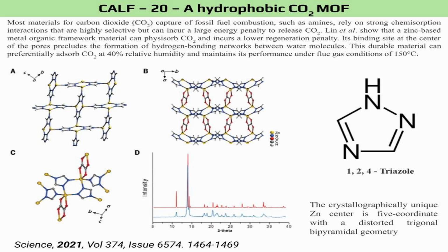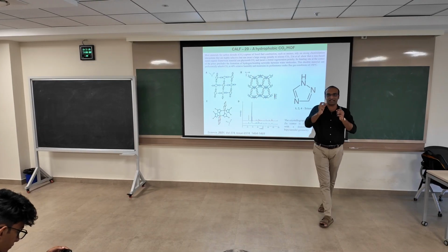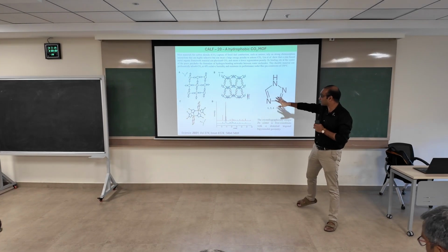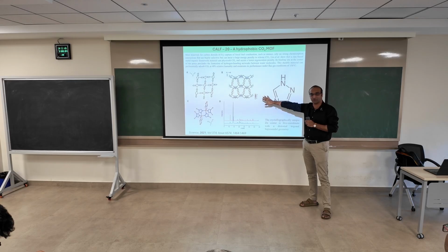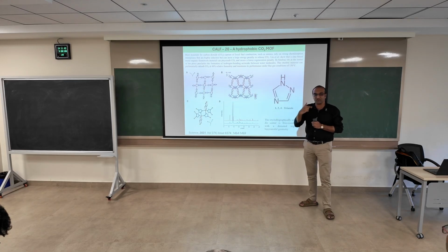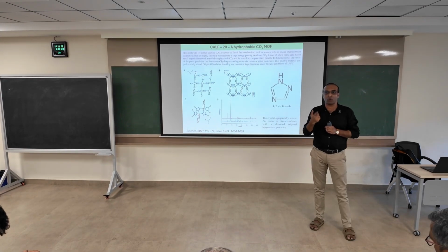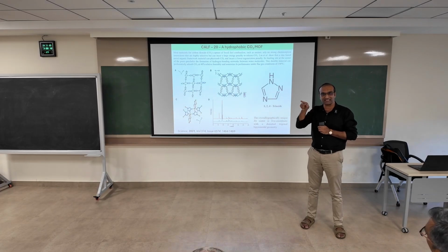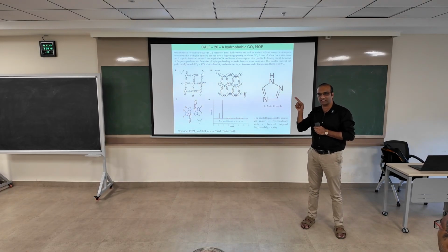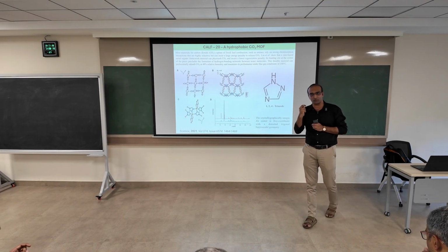On top, it's one layer where you have this zinc and this coordinated weakly, okay? And then you have these layers in between, they're connected through these oxalic acid linkages, okay? But the unique thing about this MOF, and the reason why I'm showing it, is it has a preferential adsorption for CO2 over water. So most of the gas that comes out from the flue gas will have high humidity, a lot of water vapor, okay?